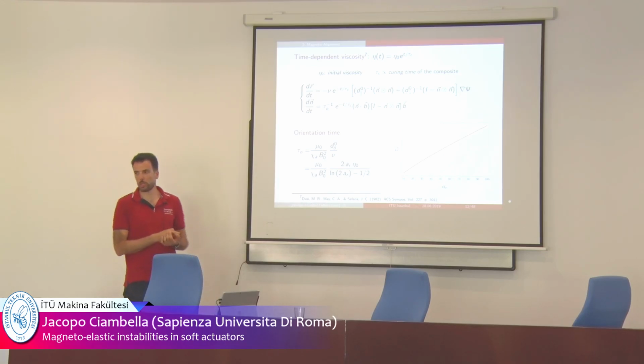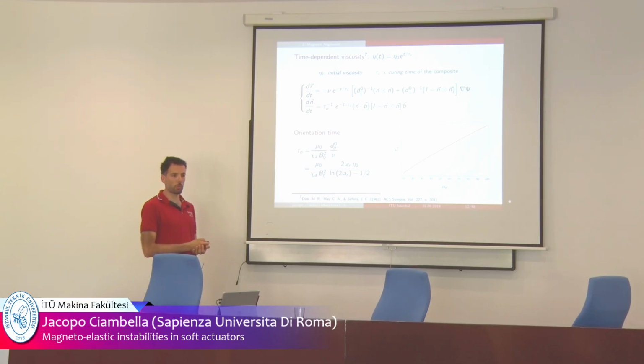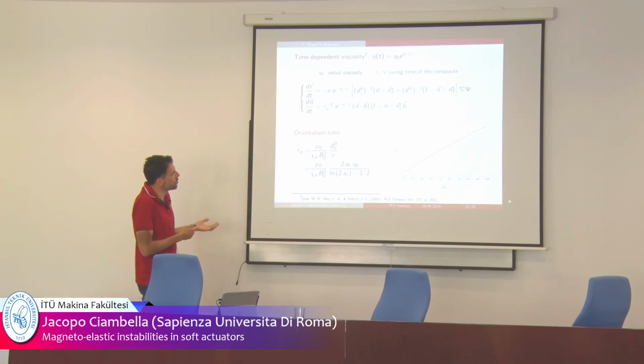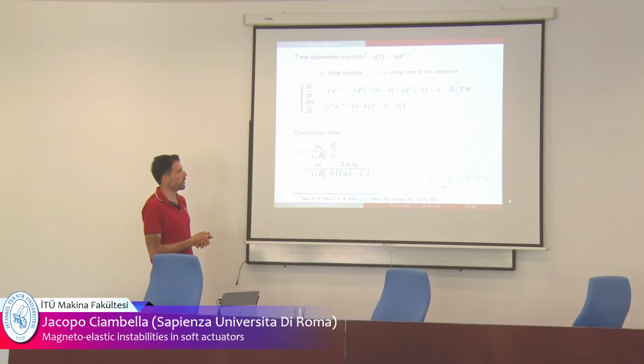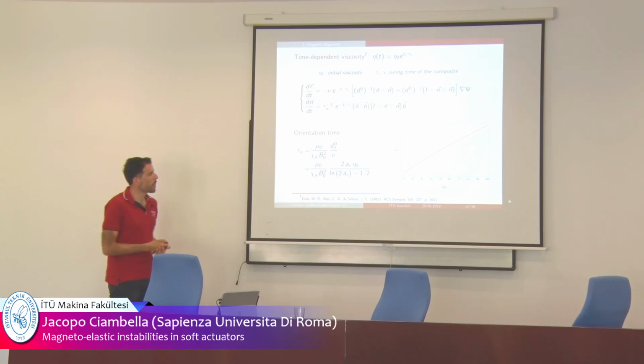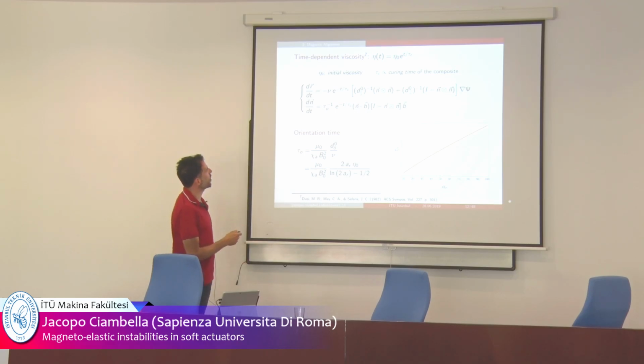Eta 0 is now the initial viscosity of the solution, and tau c is what I call here the characteristic curing time. So you can change very easily. You put this expression in the previous equation, you get the equation for the translational velocity, and notice that this equation only depends on the gradient of c, so on the force. The rotational velocity only depends on the mutual direction between n and B. This can be solved in closed form, and the orientational time depends on a characteristic time, which I call here tau O. Tau O is a characteristic orientation time.